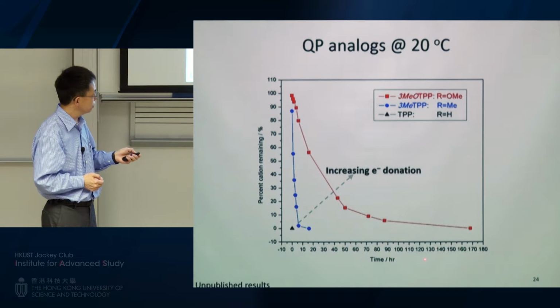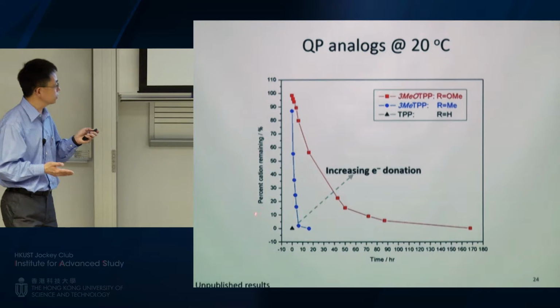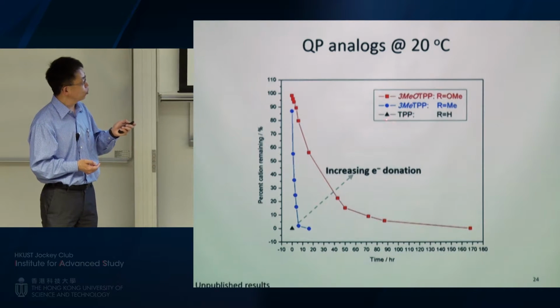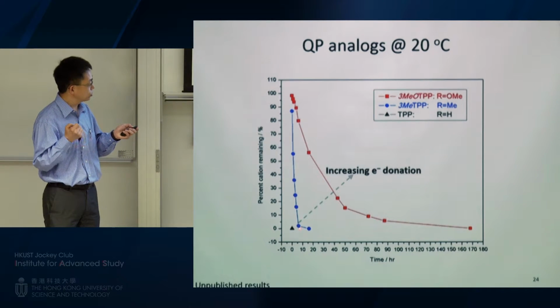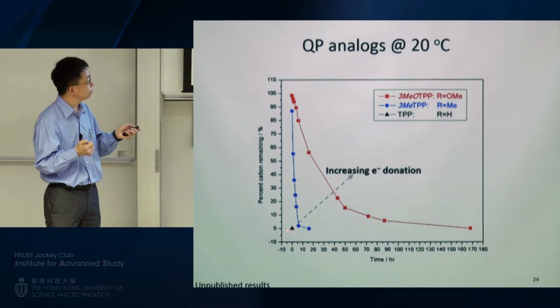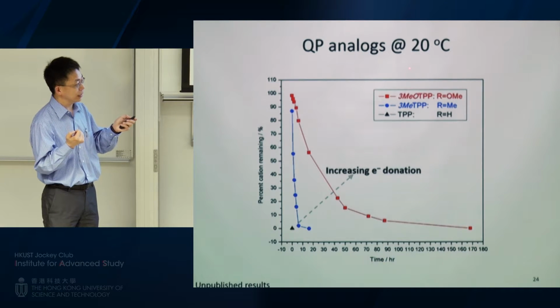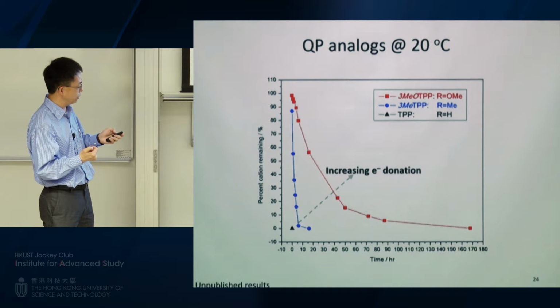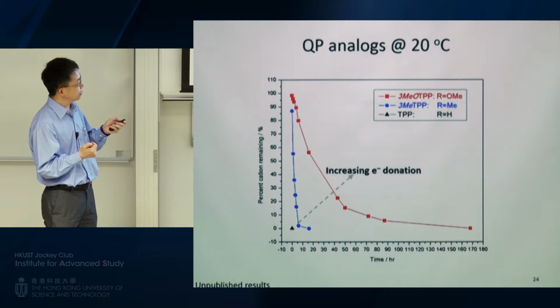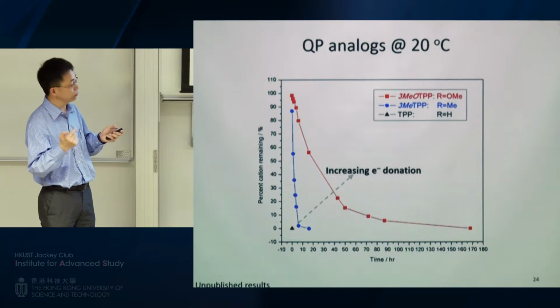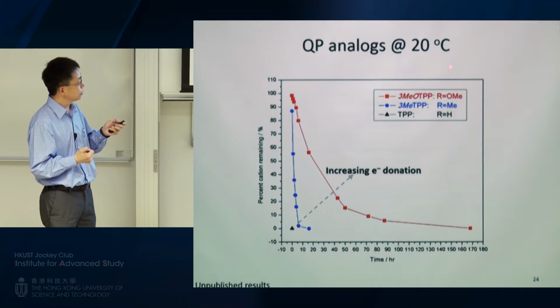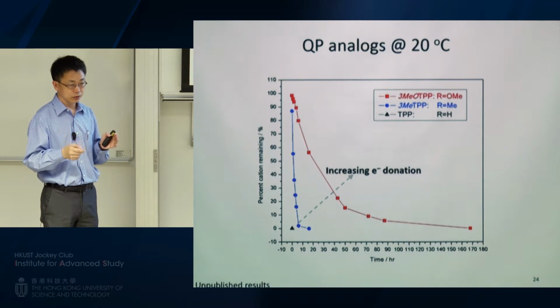So this is the number of hours of the test, and this is the percentage remaining, again, just like before. So what we see is, if you have no substitution, this one basically would just go bad right at the door. It wouldn't get out. And the other thing I want to point out is this is a 20 degrees C test instead of 80 degrees C. So it's a much milder test already, and this guy doesn't even get out of the door. And then if you look at the 3 methyl groups, slightly better, but not by a whole lot. And if you look at 3 methoxy groups, it's already much better. So this tells us clearly the electron donation is very important for protecting the center atom, because methoxy, as I showed you, is a much stronger electron donating group, because all three have very similar steric hindrance, because you have just one group.